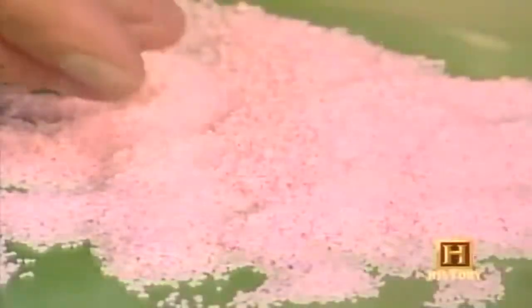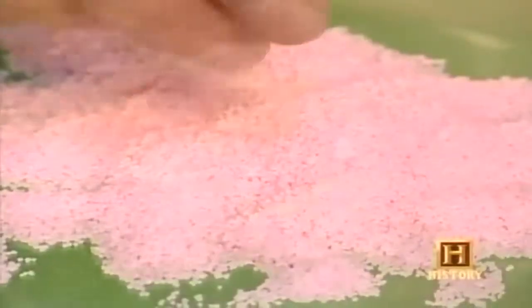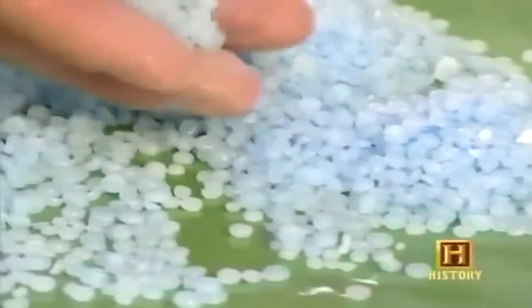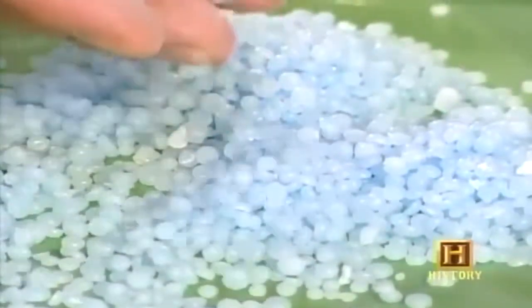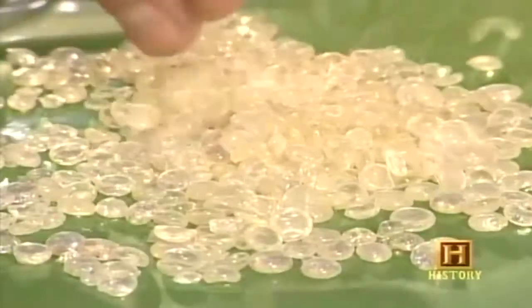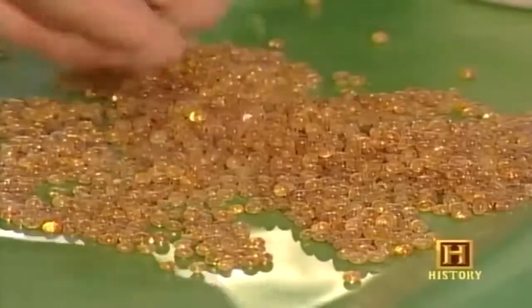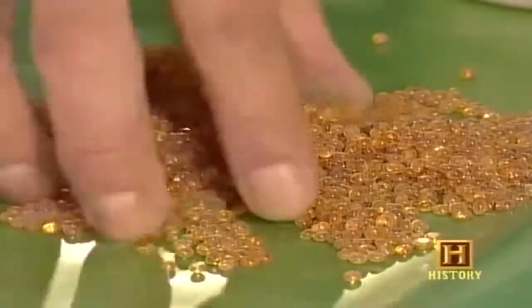And just as an example, here you have an antioxidant which protects the tire from attack by oxidation. This is a resin. It helps it to adhere to the metal. This product is a wax that helps in the processing of the rubber and also helps the tire to stay black. This is another antioxidant. This product is an anti-ozonant, so same purpose except this time to shield the tire from attack by ozone. You would have anywhere from 3 to sometimes up to 8 of these different chemicals in a given formulation, but when you add it all together, it would only represent 3 or 4 total percent of the weight of the rubber compound.